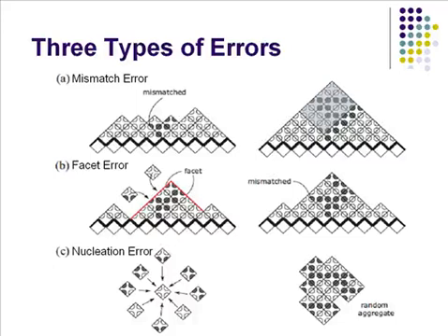So it must fall off fast. But before it falls off, another tile comes and connects here with two bonds, then both of those two pieces are stabilized now, so there is no chance to get out of this mismatch.